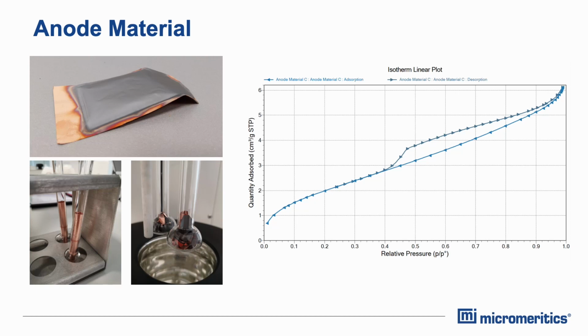When performing physisorption experiments, we have to think about sample preparation, especially when working with electrodes or generally with foils. From the pictures on the left side, you see that different ways are thinkable. We already tested in our labs, on the one hand side, rolling up electrodes, like you see on the left picture, but we also performed tests where we just simply cut the electrode in smaller pieces. From our experience, both ways work, but a lot of customers prefer rolling up the electrodes because it doesn't have the risk of destroying the surface of the active material.